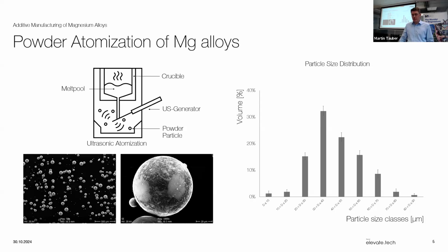And the good thing is with this machinery, we are capable of forming really round spherical particles, which is one of the main needs that have to be met for additive manufacturing in good quality. On the right-hand side, you can see that from this process, we usually get different grain sizes, and we try to narrow the grain size down as much as possible. So after the melting of the material and the atomization, we're also going through sieving processes to have a really narrow grain size distribution to have a good powder for our machining in the LPBF process.